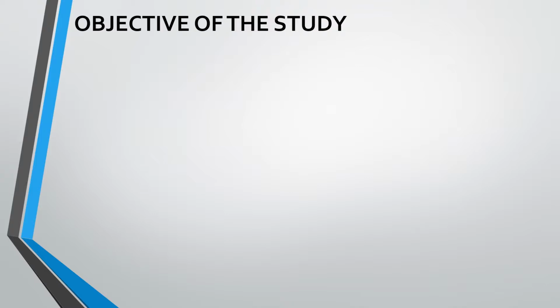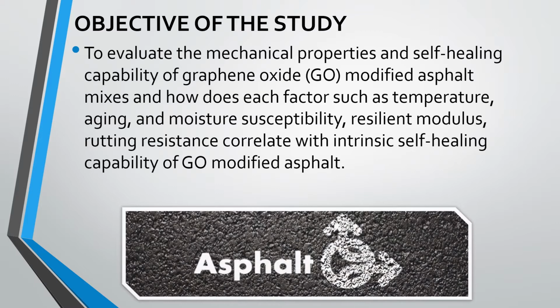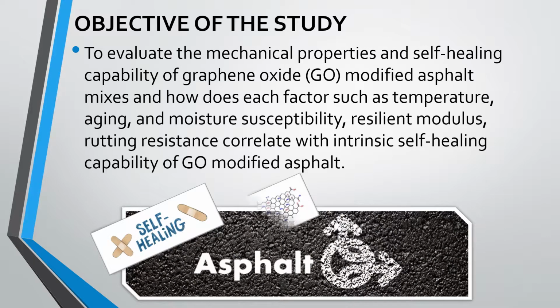So, the main objective of this study is to evaluate the mechanical properties and self-healing capability of graphene oxide modified asphalt mixes, and how each factor, such as temperature aging, moisture susceptibility, resilient modulus, and rutting resistance, can be correlated with the intrinsic self-healing capability of GO-modified asphalt.